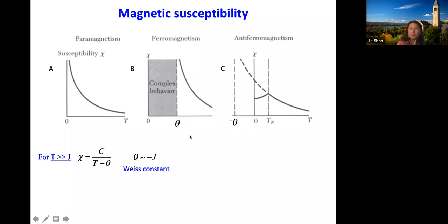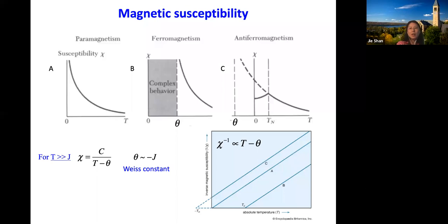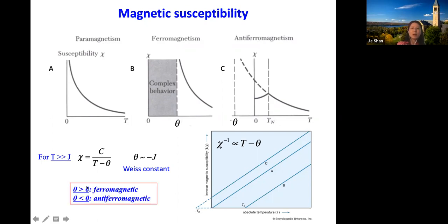It's a little bit cleaner if you look at the 1/susceptibility, and they all follow a linear dependence as a function of temperature. For paramagnetism, the line, if you extrapolate from high temperature to low temperature, goes to 0. For ferromagnetism it goes to some positive number, and for antiferromagnetism it goes to a negative temperature. In one sentence, if you look at the high temperature behavior and extrapolate, looking at those constants, you'll be able to tell about the nature of the interaction. And this is exactly what we did. As I said, positive is ferromagnetic, and negative is antiferromagnetic.